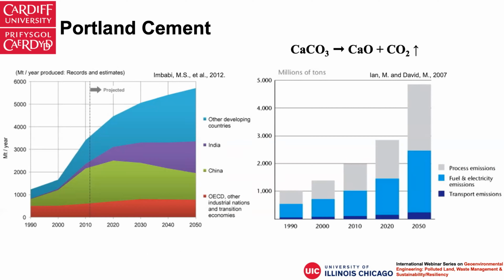That is mostly due to the more and more constructions and urbanizations in the developing world, while the developed world has almost plateaued. In order to produce Portland cement, in the raw materials, we need to have calcium carbonate, basically from limestone. That process decomposes calcite or limestone to calcium oxide and carbon dioxide. That forms a large part of the carbon dioxide emissions from the production of Portland cement. And that is chemically unavoidable, because as long as you need Portland cement clinkers, you definitely emit that amount of carbon dioxide from the decomposition of calcite. Another large proportion of carbon dioxide emissions comes from the fuel and electricity emissions in the whole process.